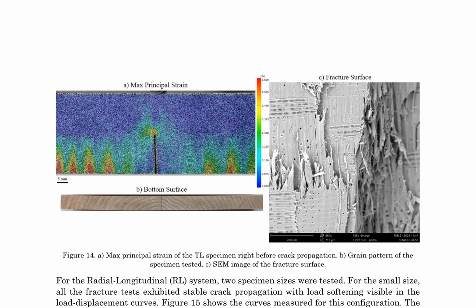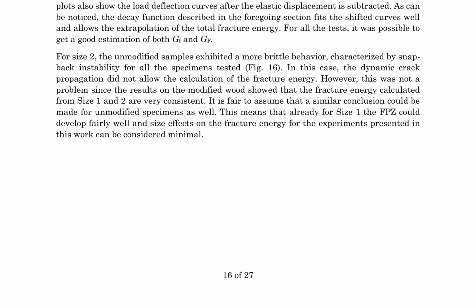In contrast, the larger size specimens displayed brittle behavior, characterized by snapback instability, precluding the calculation of fracture energy, figure 16. However, modified wood samples from the larger size yielded consistent fracture energy values with those from the smaller size. This suggests that a similar conclusion could be drawn for unmodified specimens, implying that the fracture process zone, FPZ, can develop adequately even at the smaller size. Consequently, size effects on fracture energy can be considered minimal in the experiments presented.